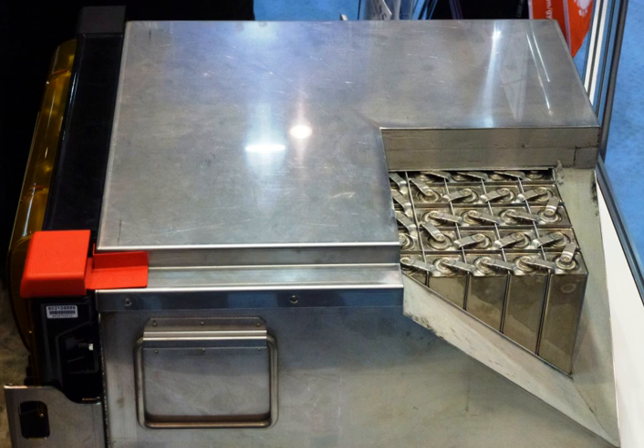In 2015, GE abandoned the project. Sumitomo developed a battery using a salt that is molten at 61 degrees Celsius, far lower than sodium-based batteries, and operational at 90 degrees Celsius. It offers energy densities as high as 290 watt-hours per liter and 224 watt-hours per kilogram, with charge/discharge rates of 1C and a lifetime of 100–1,000 charge cycles. The battery employs only non-flammable materials and neither ignites on contact with air nor risks thermal runaway, eliminating waste heat storage or fire and explosion-proof equipment and allowing closer cell packing. The company claimed it required half the volume of lithium-ion batteries and one quarter that of sodium-sulfur batteries.